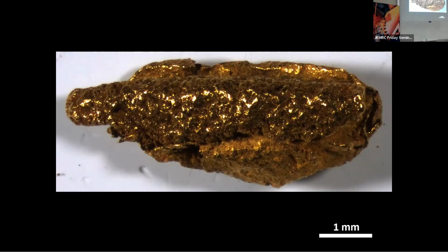And the one thing that she did that was really cool, because we wanted to say that microbialites are responsible for cementing beach rock, was she added excess strontium into the seawater. It naturally has 8 ppm. You can bump it to 40 without saturating. And so we were able to trace the strontium to show us what the new microbialites were that had grown within the last 2 months. And they were all full of fossils. So the cement was biogenic within that system.